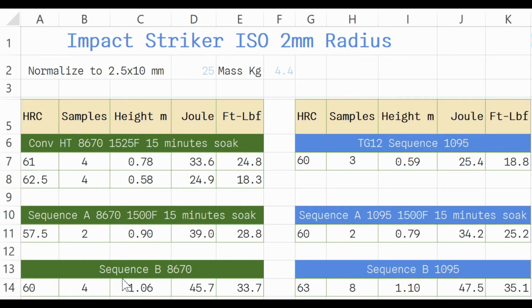And then I did another sequence, and this time we got 60 Rockwell here for 8670. We got 4 samples, and the result is 33.7 foot-pounds. So recall again, I extrapolated the value up here as about 28.8 foot-pounds. Now this sequence here, B, gets a better result. We got about 4.9 foot-pounds improved.